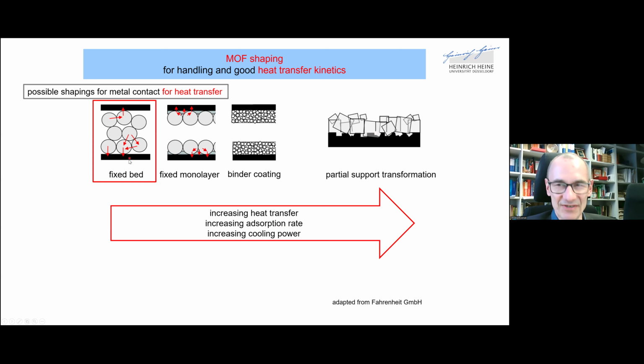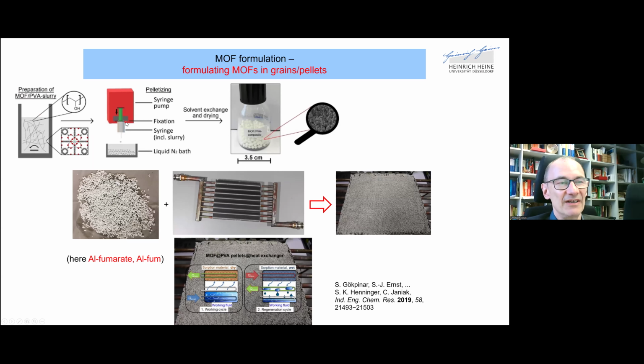So we start with the left one because it's most simple. And as chemists, we cannot do everything. So we just showed that schematically it is possible to have a MOF made in spheres and then brought in between the lamellas of a heat exchanger. In order to transform a MOF into spheres of 2 millimeter, we have to bring in an organic polymer, but only to a weight percentage of 10%, which then binds the MOF powder into mechanically stable spheres. So these spheres you see down here again. Here you see a heat exchanger, and then in between the lamellas of this heat exchanger, we can put the spheres. From below there is a net so that they don't fall through.